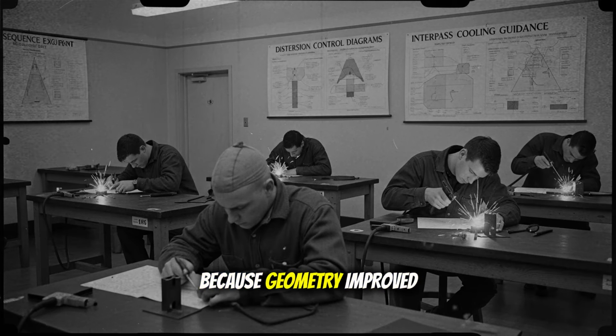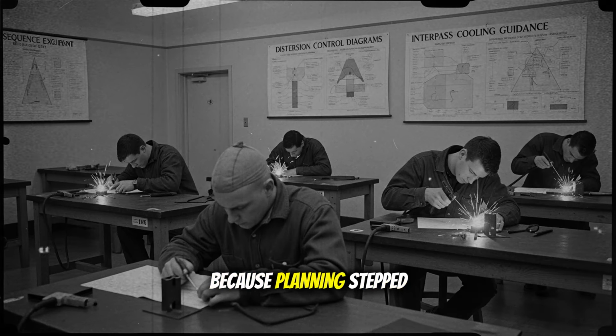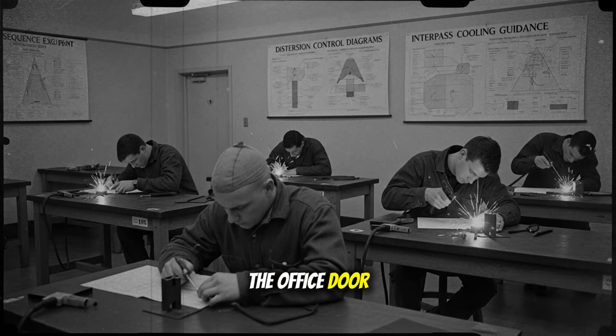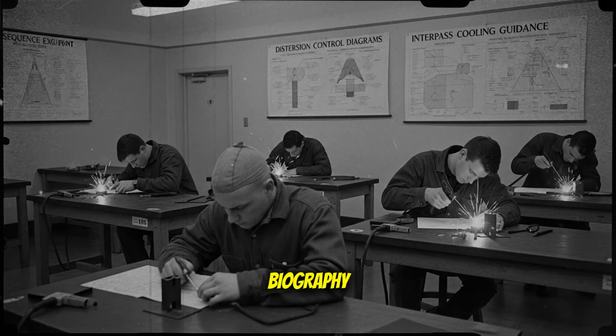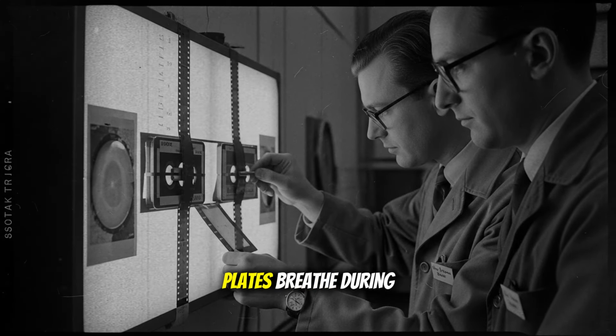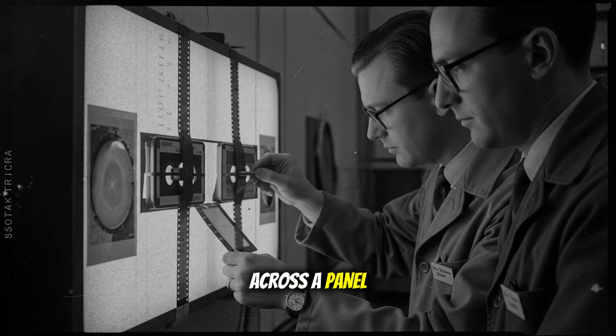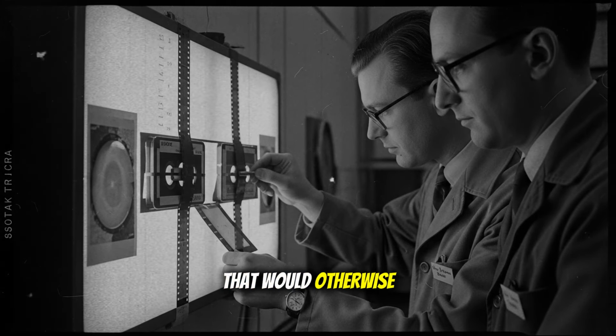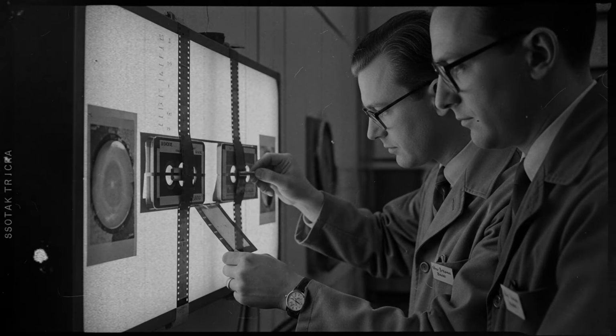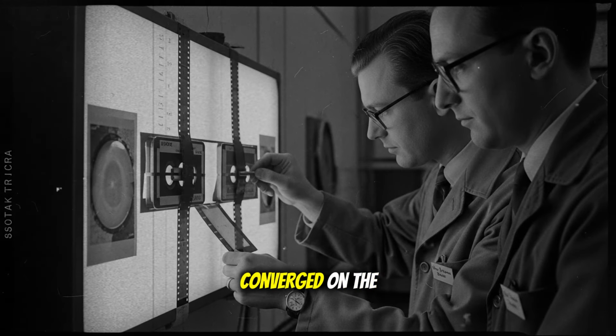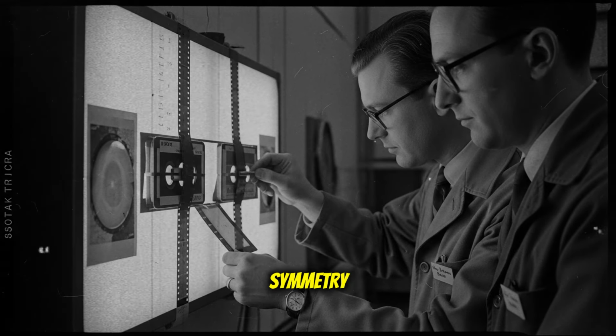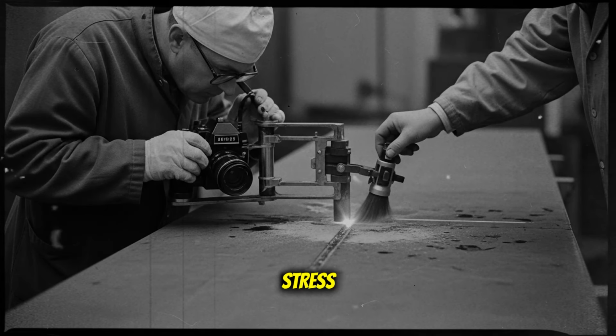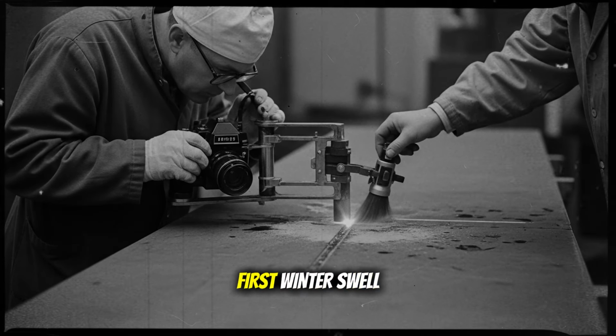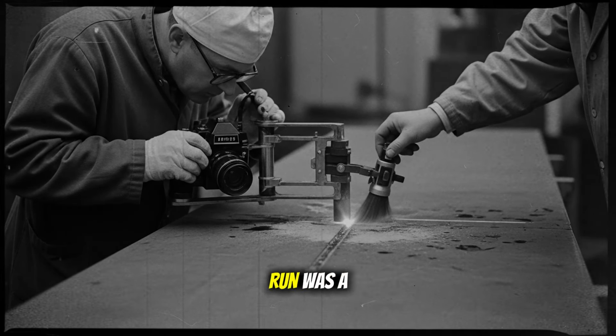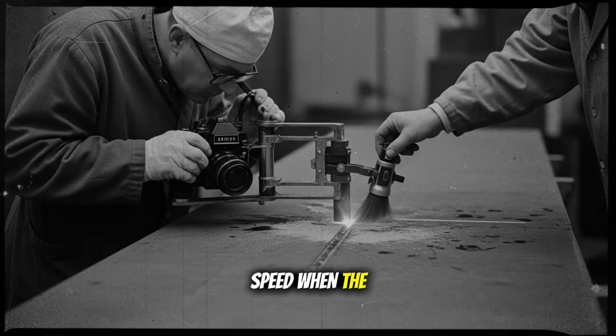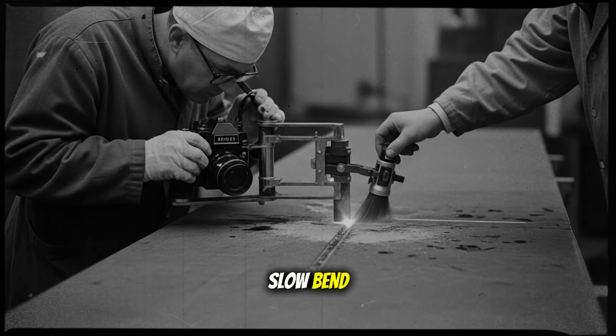Productivity improved because geometry improved, and geometry improved because planning stepped into the shed and refused to leave engineering at the office door. Discipline and sequence changed the metal's biography, because the order of welds decides how plates breathe during cooling, and alternating runs across a panel can lower peak residual stresses at weld toes that would otherwise become crack origins under cyclic load in service. Analytical studies and yard experience converged on the same conclusion: skip welding patterns, symmetry, and restraint reduce both distortion and stress, raising panel capacity before a ship ever meets the first winter swell. Every avoided continuous run was a line the ocean would not get to read back at speed when the temperature dropped and the hull went into a long, slow bend.